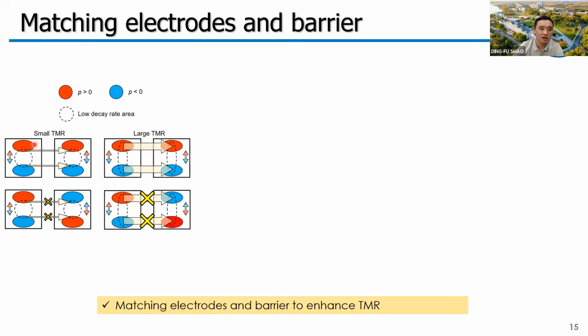For example, here we have well spin polarized conduction channels. But if in the barrier the slowest decay rate is located here, the overlap between the conduction channels and the slowest decay rate area is very small. In this case, the transmission for the parallel state and the antiparallel state do not have a big difference. So we can only have a small TMR. But if the overlap is very large, we can expect a very large TMR.